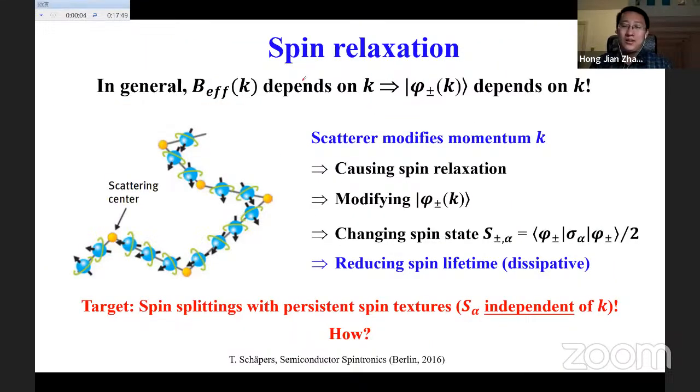But to utilize the spin transistor, we should avoid spin relaxation. So what is spin relaxation? Typically, because the effective magnetic field depends on K, the quantum spinor state depends on K as well. During electronic transport, because of impurities, defects, and phonons, the electrons are scattered. After scattering, the electronic momentum is changed, and then the quantum state is modified as well. The spin magnetization is a distribution in K space, so if K is modified, then usually S is modified. It means scattering kills the electronic spin, and the spin transport is somewhat